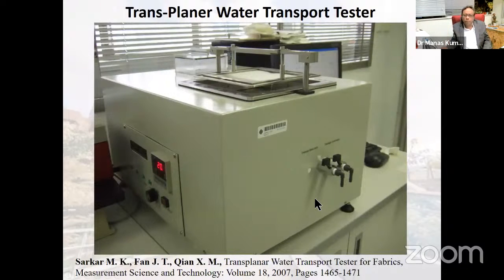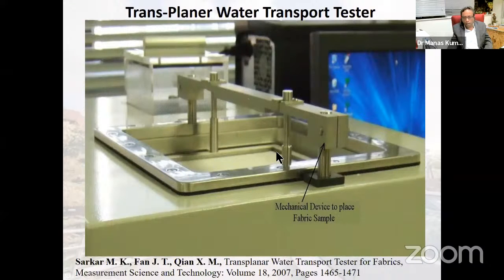For measuring this property, because this is a very highly absorbing material, we developed a unique tester. We call it the plant structure transplanar water transport tester. It measures the water absorption property in real time. We put the fabric here. When you turn on the switch, it automatically goes down, and once it touches the water bed at the bottom, the amount of absorption is immediately recorded in the computer.